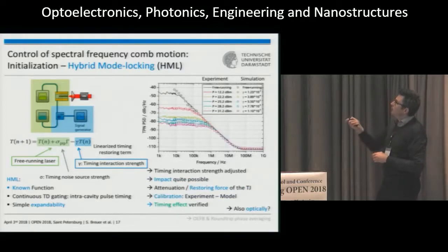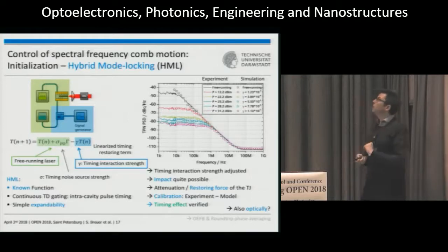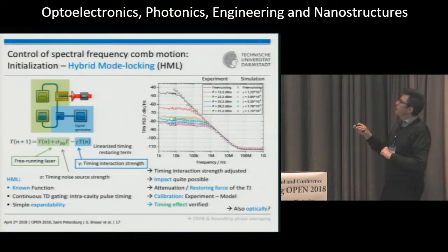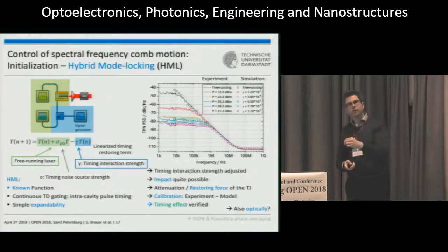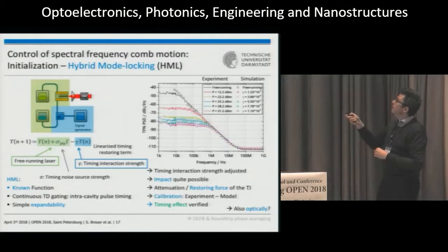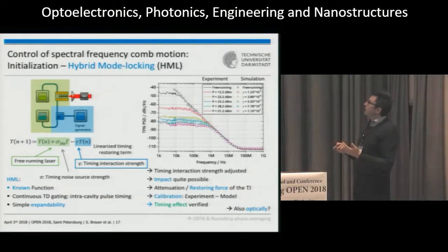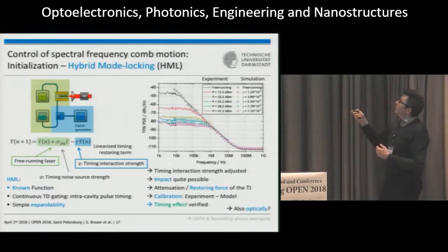So this is a timing phase noise power spectral density, a measure for the spectral motion stability of the mode comb as a function of the offset frequency. You can see the experimental part as the solid lines for different electrical injection powers. The higher the injection power, the better the stability and the lower the phase noise. Now the only thing that needs to be done is adjusting this gamma parameter, this timing interaction strength, because we don't know it.